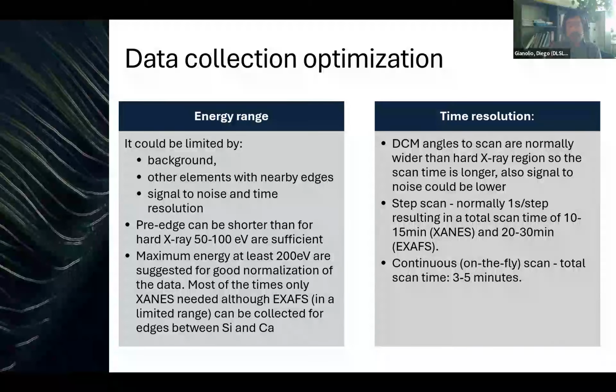So normally the pre-edge is a bit shorter than for hard X-rays, again due to the acquisition time needed. So 50 to 100 eV are normally sufficient to subtract the baseline, and the maximum energy is again much shorter, but our suggestion would be always to collect at least 200 eV in order to help the data treatment, in particular the normalization of the data.